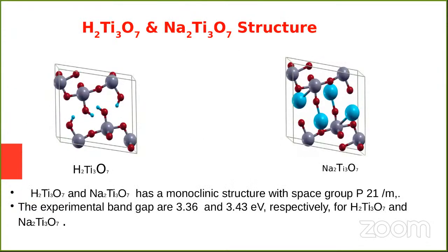And now here is our structure, the structure of hydrogen titanate and sodium titanate. Both structures have a monoclinic structure with space group P21/m. And the experimental band gap for hydrogen titanate is 3.36 electron volt and 3.43 electron volt for sodium titanate.